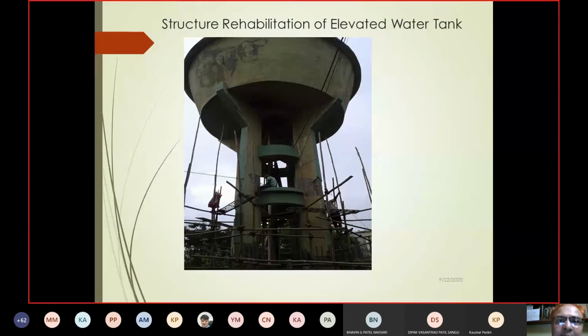This is the structural rehabilitation of the elevated water tank. The size, the diameter, is 10 meter, and certain cracks and delamination have started. This is a sugar factory. They contacted us to repair it, and we tested with rebound hammer and UPV, but the concrete strength is not more than 13, 14, 15, not more than that.